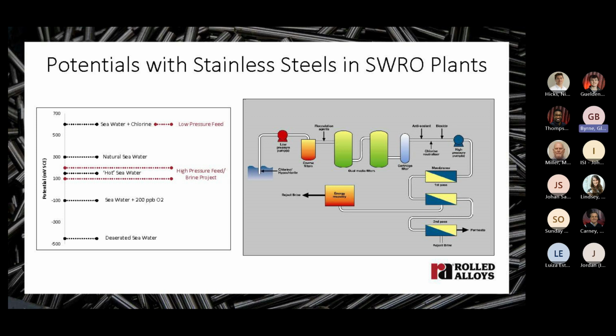The dechlorination is done by adding chemicals like sodium metabisulfite, and this is an oxygen scavenger by nature, and it pulls the potential down to the range plus 200 to plus 100 millivolts, depending on the dosage. And this is a range where the membranes tend to work at their best. So we have this condition up to the membranes, where after the chlorine neutralizer, we have treated seawater with a chloride content typically of 20,000 ppm at plus 200 to 100 millivolts, going up into the HP pump and beyond. After RO, we have two lines.